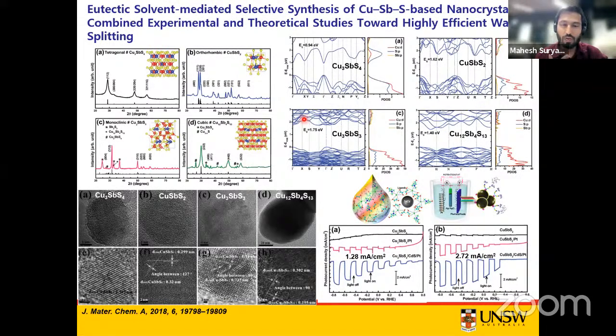And when the solvents become more and more viscous, we usually have difficulty washing the nanocrystals prepared using those solvents, let's say vegetable oil in our case. So the reason we moved to the deep eutectic solvent is that its viscosity is very low, which helps us wash those nanocrystals quite easily. And again, this deep eutectic solvent is non-toxic. So using this deep eutectic solvent, we synthesized four different phases of copper antimony sulfide nanocrystals, which have a band gap, of course theoretically predicted, ranging from about 0.94 to about 1.75 electron volt. That again suggests that these are good compounds to harvest the maximum visible light absorption.